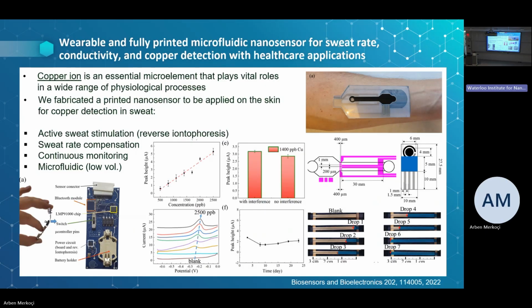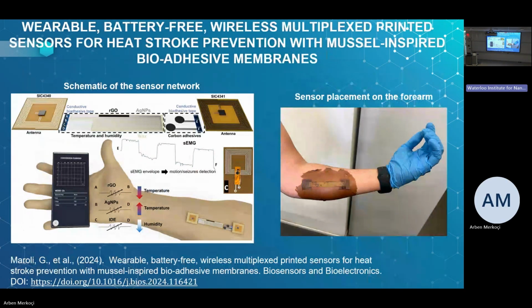This is based on a 3 electrode system using electrochemical stripping analysis. So this is a very, very powerful technique for heavy metal detection. So we can detect heavy metals, for example, in this case, copper in sweat. We did also some simple microfluidics control to see that we are able to control the sweat underneath, so the interface between the skin and the sensor. Did some electronics for this because we wanted to communicate the smartphone with this sensor and to get some very nice results for copper.